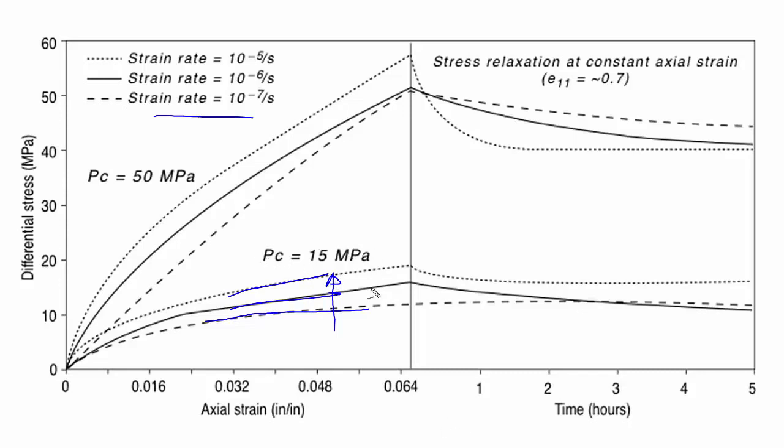Here it's also been plotted as a function of confining pressure. In this case, it's a triaxial test where a sample like this is put in a bath of confining pressure, a hydrostatic confining pressure of 15 MPa, and then it's squeezed from the ends mechanically. And then the response is measured. You can see that not only is the material rate dependent, in the sense that the faster I load it, the elastic moduli goes up, it's also pressure dependent.